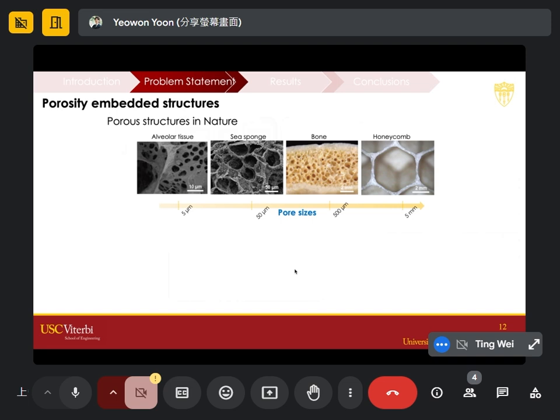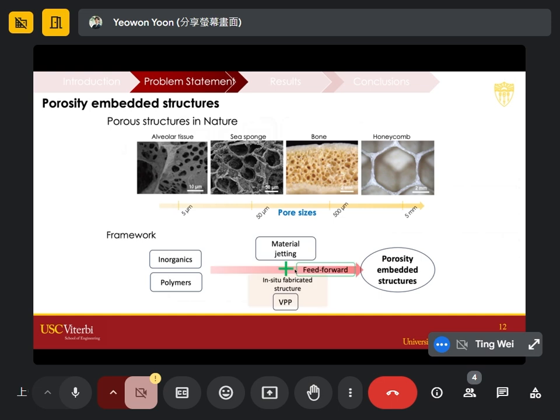For example, the lung structure has porosity because it can increase the surface area where you can interact with the gas to obtain more oxygen. The bone structure, let's say your skull, basically protects your brain well enough, but it also has pores, so that means it can be lightweight. The honeycomb structure exists in that pattern because it can minimize the consumed materials, whereas it can hold up pretty good strength using structure integrity. So the framework here is to bring two different materials and two different manufacturing approaches to create a porosity embedded structure, and that's the big scheme of the first topic.